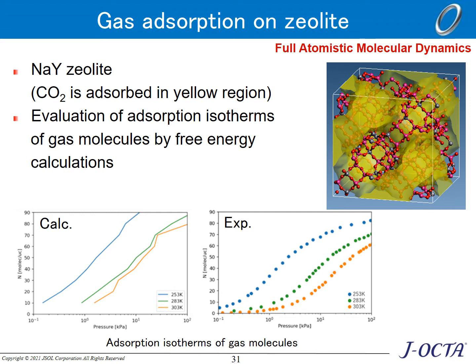Zeolite can have a structure in which Si atoms are replaced by Al, and various cations are included to satisfy charge neutrality. Here, we investigated adsorption isotherms for a NaY zeolite, which is Na ion containing FAU type zeolite. Graph shows the calculation results of the adsorption isotherms. The amount of adsorption increased with increasing gas pressure. We also examined the behavior of the gas at different temperatures and confirmed that the amount adsorbed tends to decrease with increasing temperature.